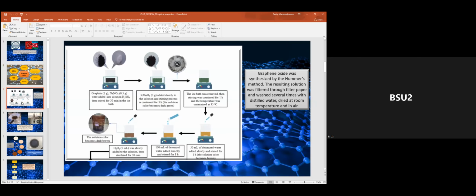On this slide, graphene oxide was obtained by Hummers' method. To synthesize graphene oxide by this method, graphite and sodium nitrate were added into sulfuric acid solution and stored in an ice bath. Potassium permanganate was added slowly to the solution, and the stirring process was continued for 3 hours. The solution color became dark green. The ice bath was removed, then stirring was continued for 1 hour, and the temperature was maintained at 35 degrees Celsius.